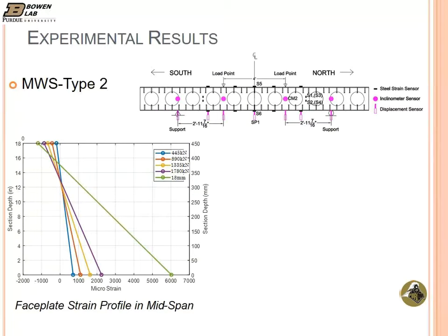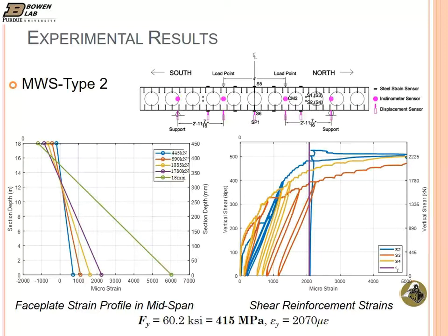Looking at the strains first, the faceplate strains at S5 and S6 up to 1,800 kilonewtons, we were in the elastic range. The specimen went up to 2,300, as you saw, and then we started yielding the bottom faceplate in that loading zone. We exceeded the yield strain, and then this time looking at the inner plates, again, inner plates also experienced strains that were larger than the yield strain. So we had yielding both in the bottom faceplate and also in the inner web plates.